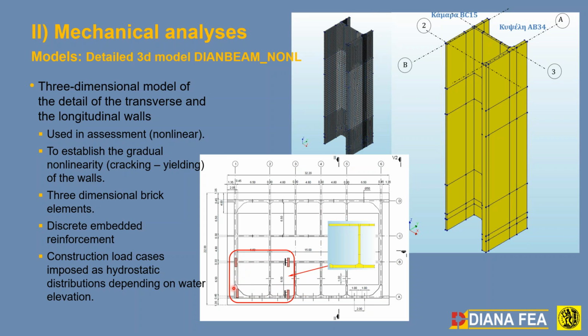full fixity conditions at this point by the perimeter shear wall, assuming roller fixity conditions because there is symmetry in this specific area. So the sub-assembly was actually like this, fixed at this point, roller in this point, and then all the way down to the mat foundation. So we actually took a sub-assembly of this caisson under the hydrostatic flotation, installation, and then the differential load case again. In this case, we used brick three-dimensional elements, and the reinforcement was modeled using discrete rebar, embedded, not sheet reinforcement.